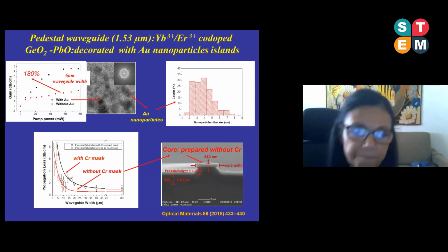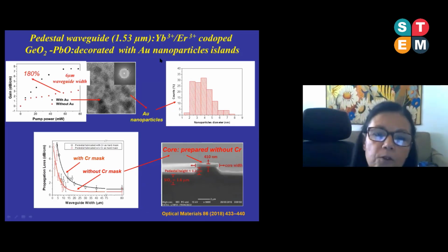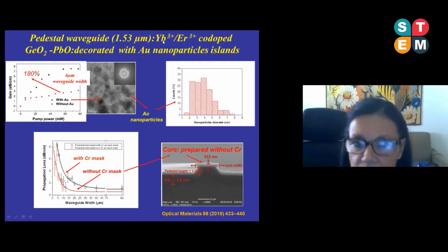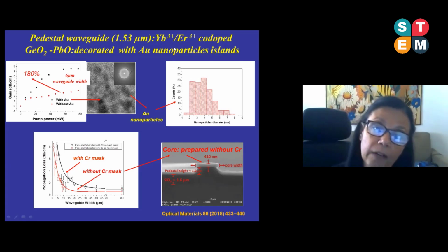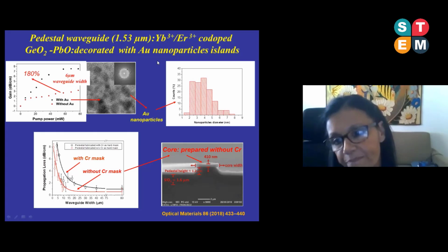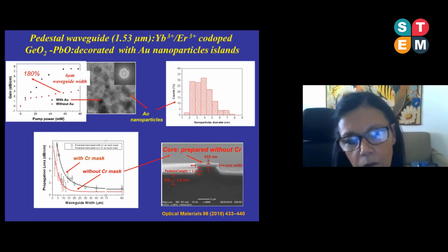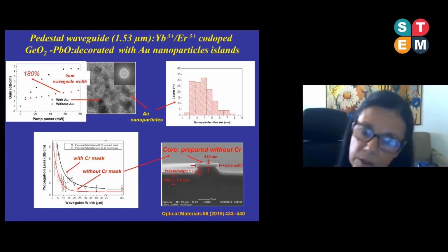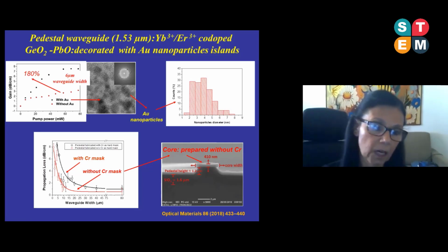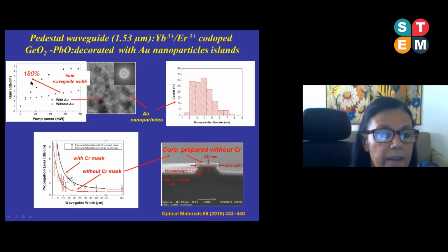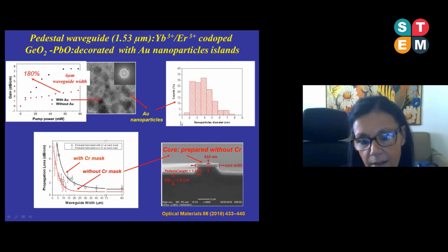Here is another result. A pedestal waveguide prepared to operate at the third telecommunication window. In this case, the core was doped with ytterbium and erbium ions. And I'd like to highlight that we use a similar setup not only to produce the waveguide, but also to determine the relative gain. We observe here an enhancement of about 180% for a waveguide width of 6 micrometers due to the presence of this island with gold nanoparticles with average size around 4 nanometers.